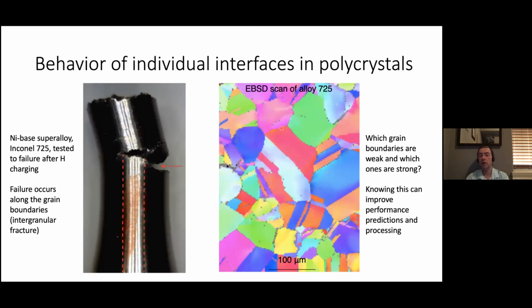So what you see here on the right is an EBSD scan, electron backscatter diffraction scan, taken in an electron microscope. And in this particular scan, you can actually observe individual grain boundaries. Right? So for example, this right here would be an individual grain boundary. I can't annotate very well, guys, I'm sorry. And we might be interested in figuring out how that individual grain boundary is going to embrittle. Is it going to be one of the stronger boundaries, or is it going to be one of the weaker boundaries? And so mesoscale studies are the ones that are going to help us to figure that out.